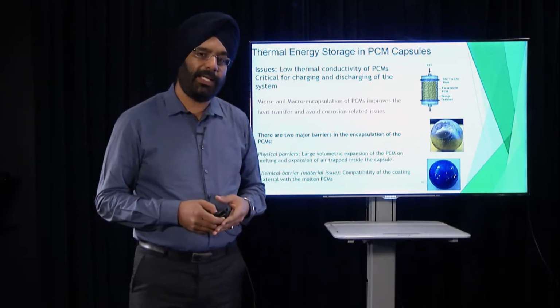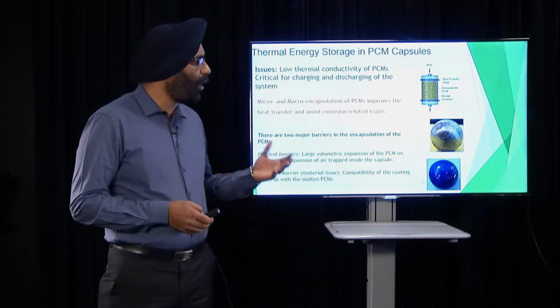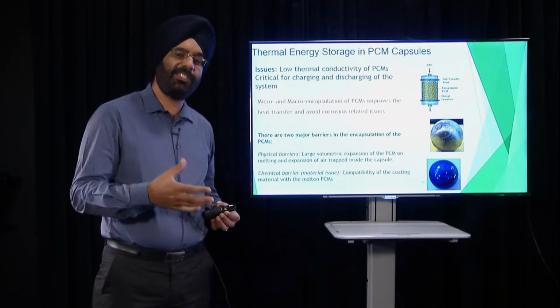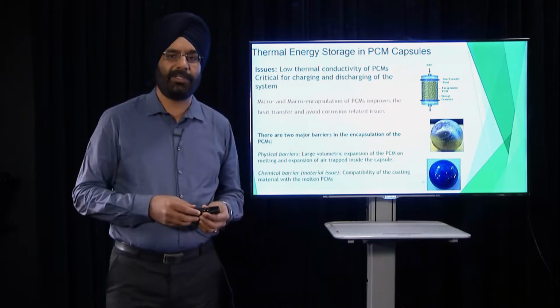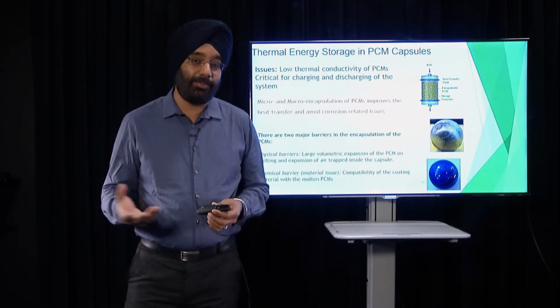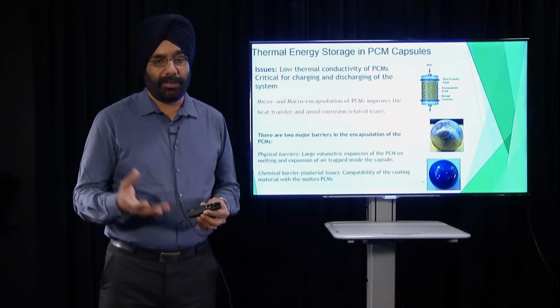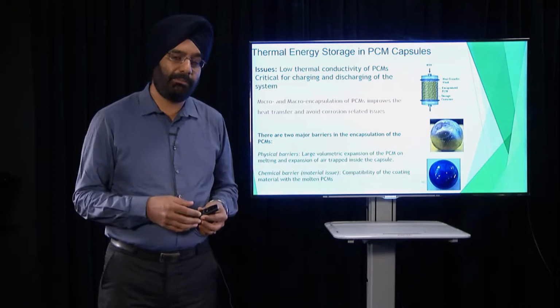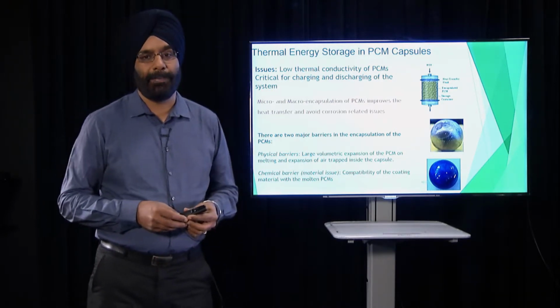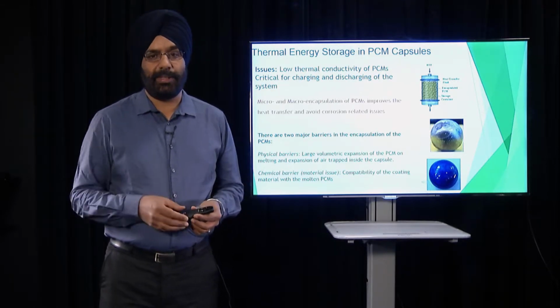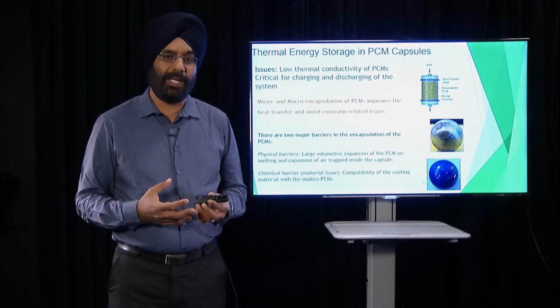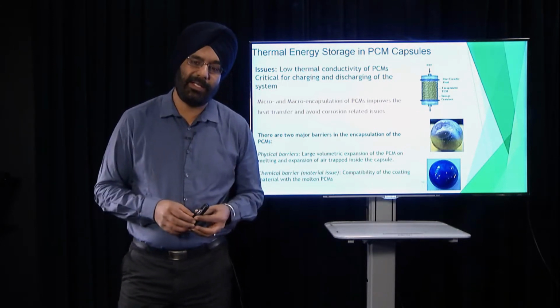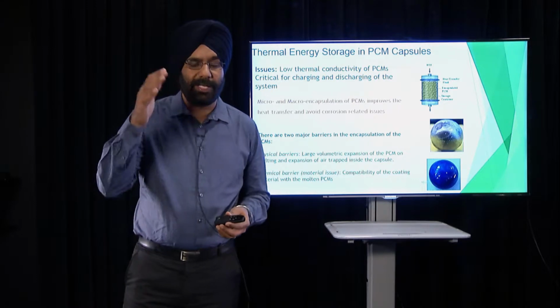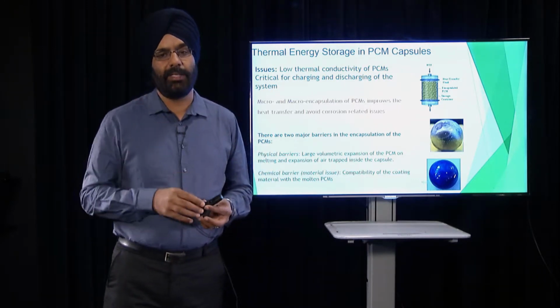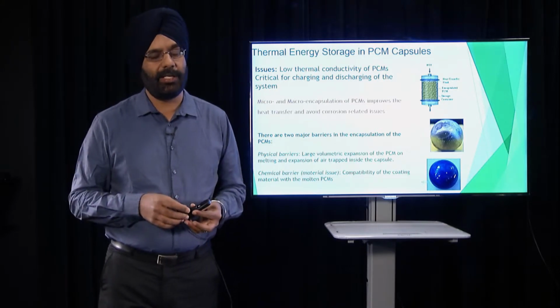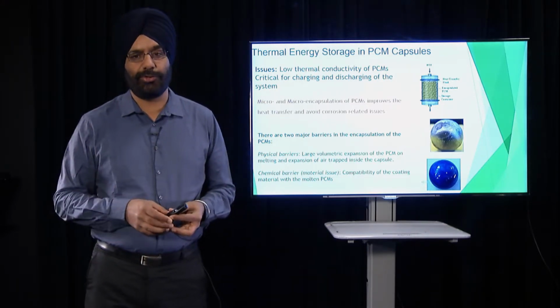So how to alleviate this problem, how to remove this problem? One way people have been trying is that in this phase change material, they add some conductive particles like small metal particles, small nanoparticles, carbon particles, graphite, and all those things. They are using metal mesh to increase the conductivity. But all those have certain issues, like with the particles, there is a density difference between the phase change material and the higher conducting particles which you are adding. So what happens is, because of the density difference, those particles either float in the phase change material when they are in molten state, or they just settle down. And there are some other issues too.